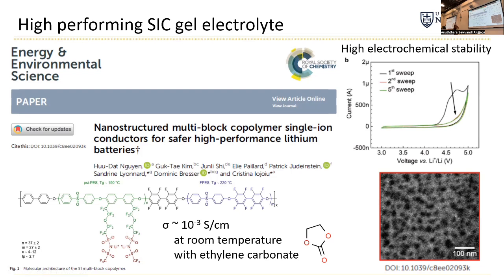And so you can see here that this polymer has a really rigid backbone. It's a polysulfone, but it's a very complicated system. So it has a hydrocarbon-type backbone here, and then it has segments that are fluorinated, and it has these side chains, so it has fluorinated side chains, and then it has these relatively large anions here, so you get lower binding energy with lithium on the end of the side chain. And this polymer, when it's exposed to these types of solvents, forms a nanostructured membrane, where the hydrophobic backbone of the polymer comes together, and then there's these channels that are full of liquid where the anions reside. And it gives you good conductivity. The problem is that polymers like these are very, very expensive to make. So there's still some work to do there.